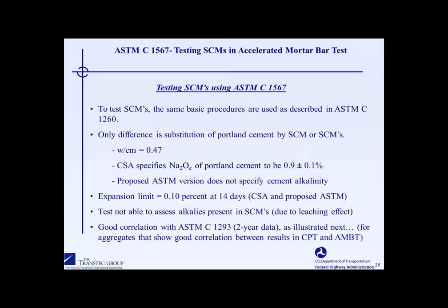I'm just going to switch gears a little bit here and talk about the accelerated mortar bar test and its use in evaluating SCMs. Again, this is ASTM C1567, the same test procedures as the accelerated mortar bar test, but again, what we're going to do now is evaluate the use of SCMs to see how much is needed to control expansion. This test has the same limitations as the accelerated mortar bar test, which means that you need to make sure that your aggregate itself is giving you the right results first before you start evaluating preventive measures, and I'll get to that in just a minute here.